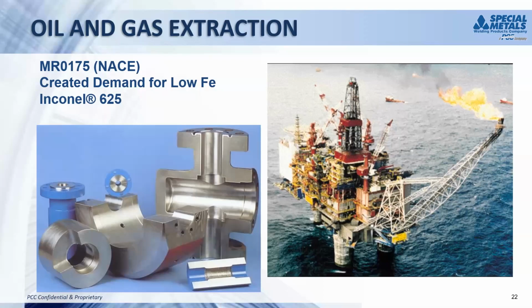The other requirement that came out of this was NACE MR0175, which actually puts a limit on the iron that's allowable at the surface on these nickel clad welds, which really led to the development of a low iron Inconel 625, which is pretty much the standard for the welding filler metal now, which at best is going to only have 0.5% iron in that wire. That just really helps you minimize the iron dilution, or minimize the iron level at the edge of that clad surface, and you just have more nickel and less iron, and therefore more corrosion resistance. Next slide.